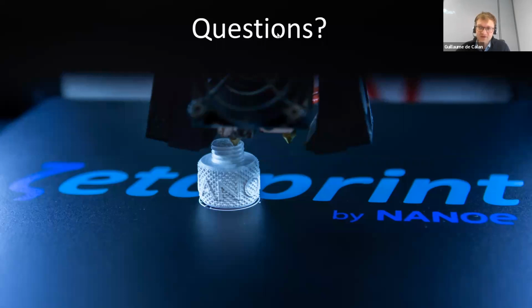Then if I go back, I say, okay, I've measured my part. I understood that the shrinkage for this part is a bit different. It's a bit more in XY and a bit less in Z, for instance, or something of that sort. If I go back to my file, compensate for this, and do a second print, I will get much closer to the final dimensions I'm requiring. And then once I have set up my process, I say, okay, I want ten of this part, or 100 parts, or whatever. So I repeat the same print with the same parameters, the same file, basically. Then the repeatability is going to be much better and will definitely, for a part of that size, be in the range of plus minus 0.1, probably even a bit less than that. I hope that does answer the question.